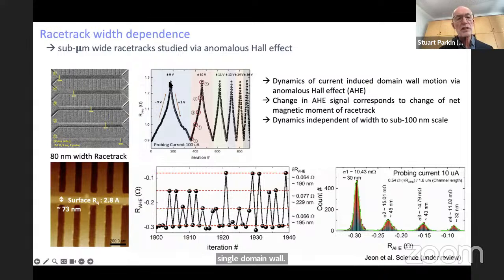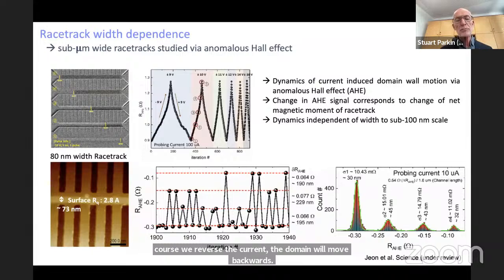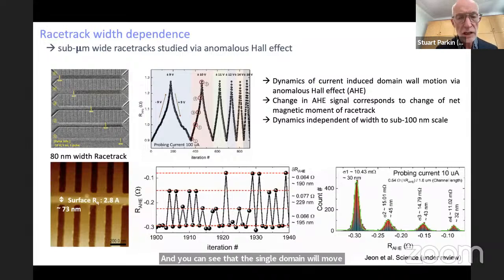And when, of course, we reverse the current, the domain wall will move backwards. And you can see that the single domain wall moves effectively pretty uniformly along the racetrack, backwards and forwards, without any significant trapping of that domain wall.